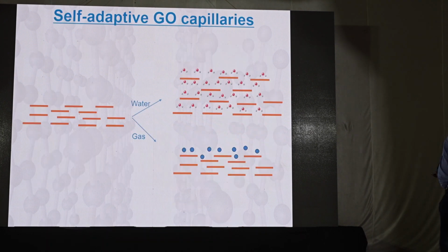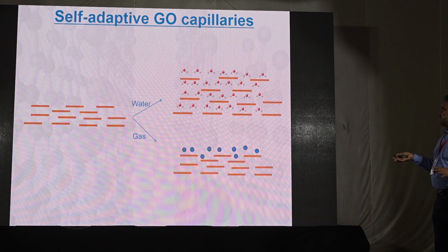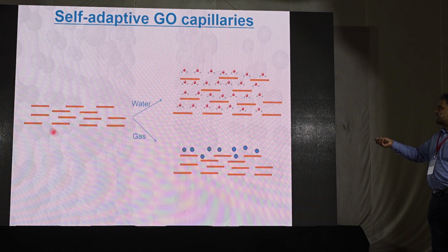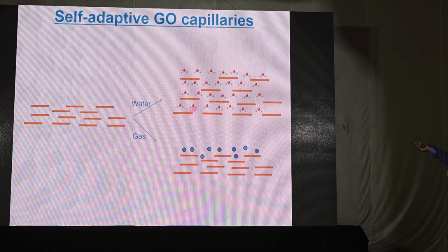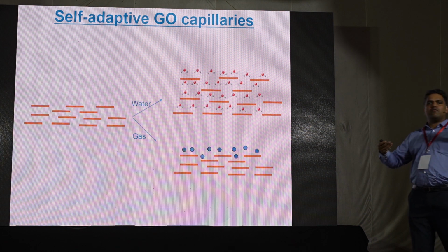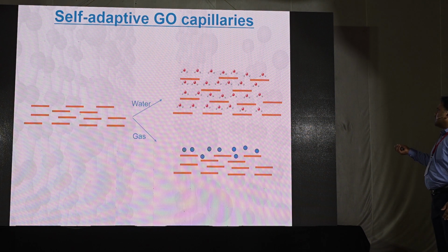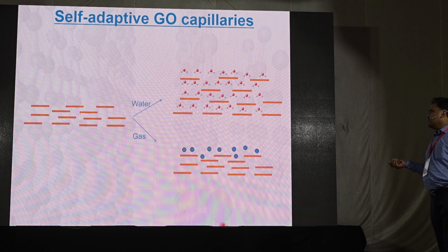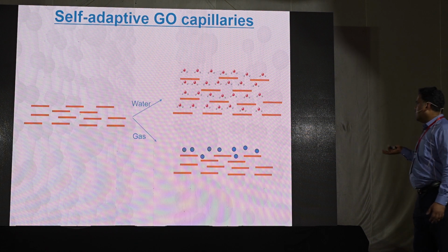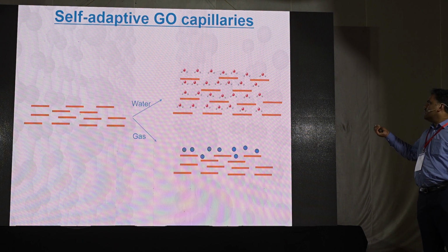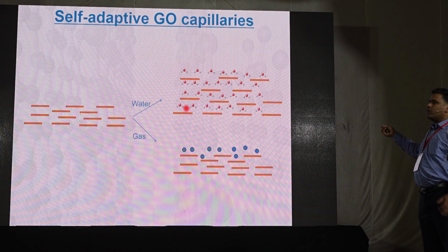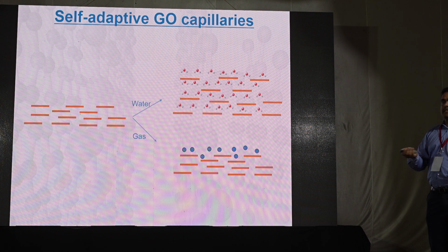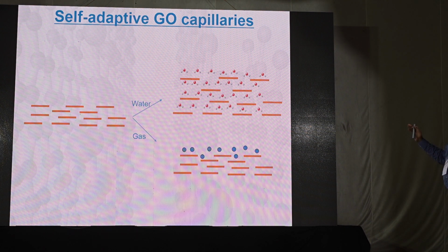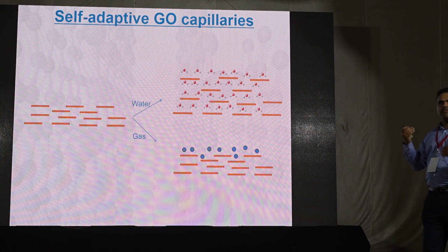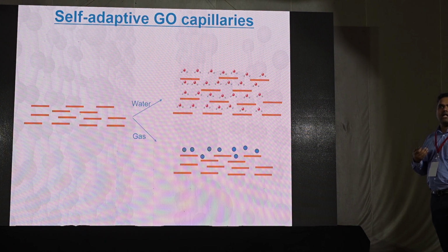One of the basic principles of this kind of membrane is that they have this kind of layered structure. When you expose it to water or certain types of solvents, like polar solvents such as alcohol, these molecules can go in between the layers and then allow the transport of that molecule from one side of the membrane to the other side. But the same membrane, if you put it in gaseous media, like helium, hydrogen, carbon dioxide, any gas, it cannot go inside. It's mainly because we call these membranes adaptive. There are functional groups on the membrane, and these functional groups interact with certain molecules that provide the selectivity in addition to the spacing. And that allows the molecules to go inside and diffuse through the membrane and gives the permeation.